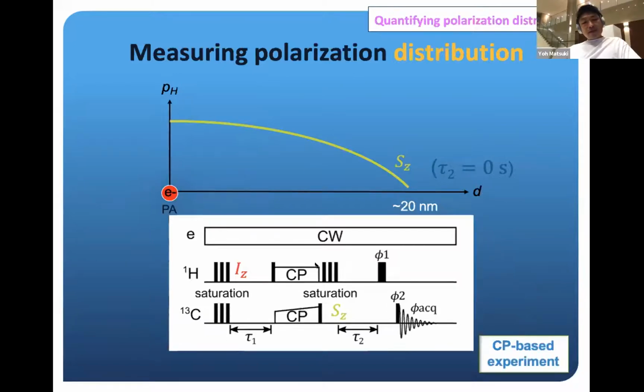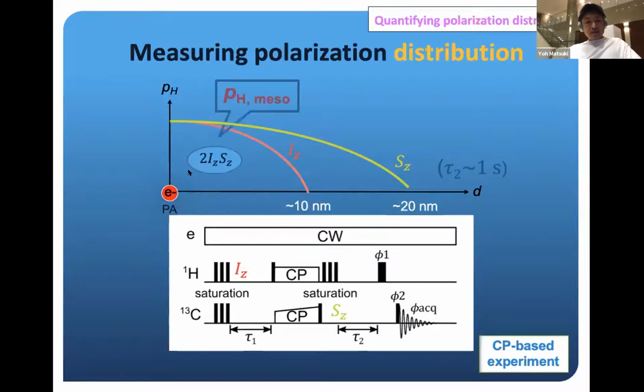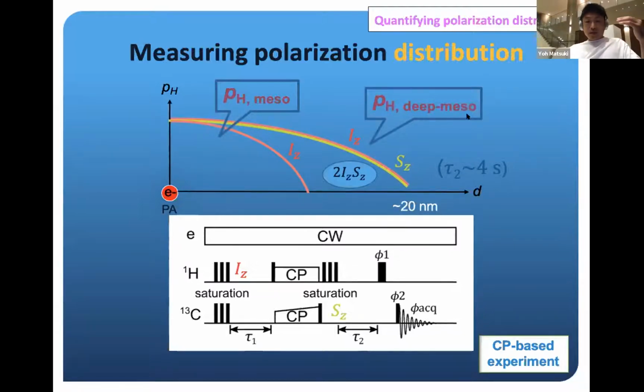So we extended this experiment to a CP-based experiment. What's happening now is the carbon is hyperpolarized first with CP, like this. And then we're going to measure the polarization level, proton polarization, as a function of tau2. With non-zero tau2, the proton polarization is coming up rapidly and diffusing, reporting the polarization level from the nearest to farthest end from the electron within meso and deep meso space over several seconds of tau2.